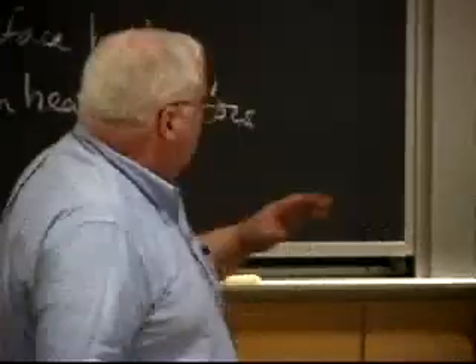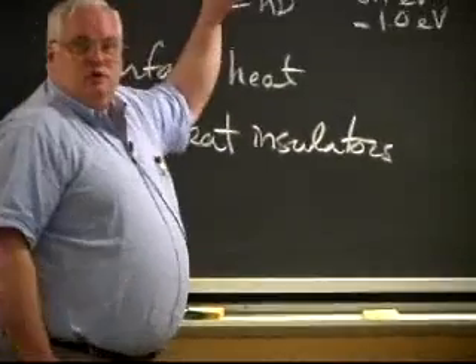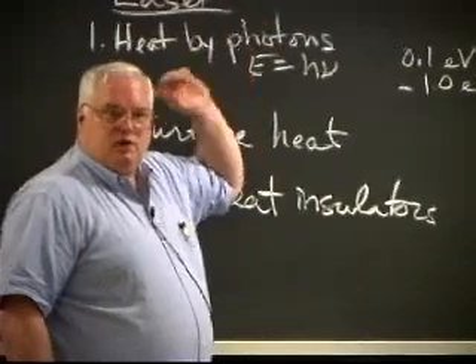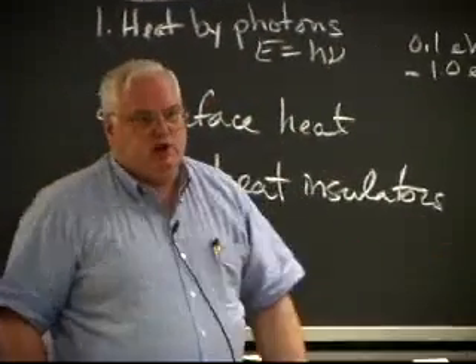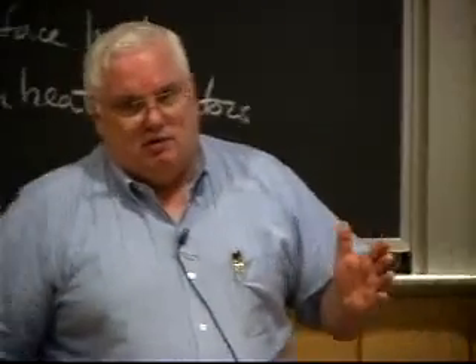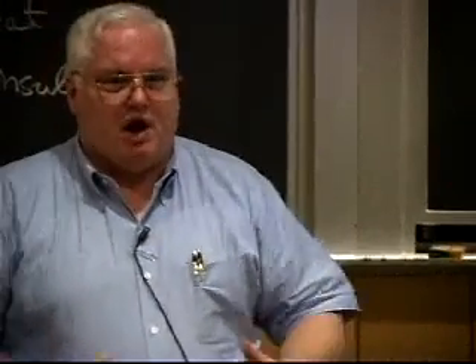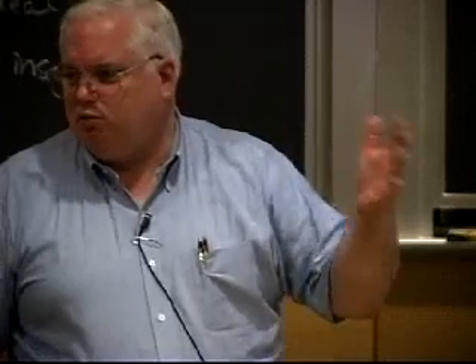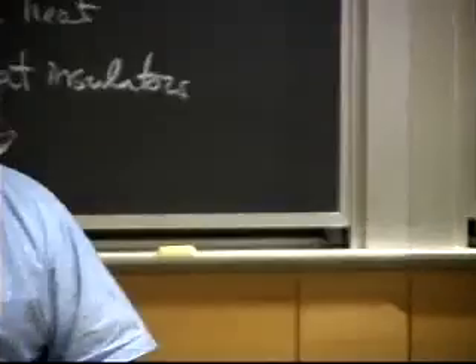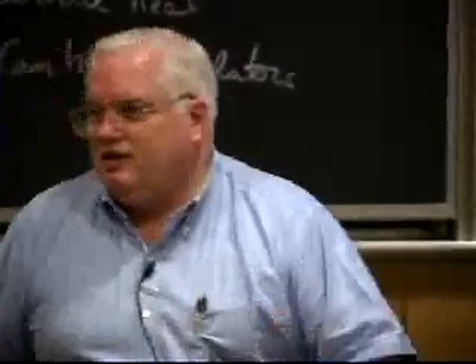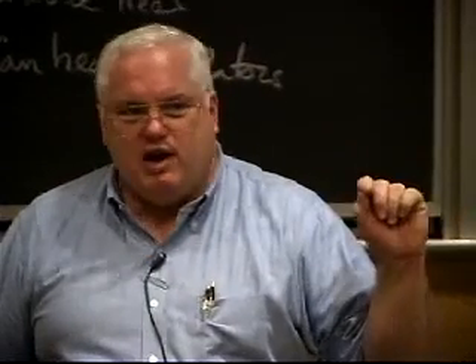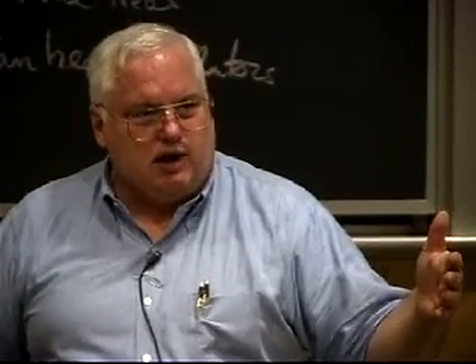And that's another reason why lasers on metals don't give you the same depth of weld pool as you'll get with electron beams. You're going to lose 70% of your heat just by reflection, which can be a problem. Which is why if you go into a laser shop, they'll have simple plexiglass, sometimes smoked plexiglass, because people think the smoke keeps the light down. It doesn't matter whether it's smoked or not. When you're talking infrared radiation, the plexiglass stops it. Smoked plexiglass, so people think they're looking through sunglasses, is really just cosmetic. Infrared radiation will not go through simple plexiglass; it'll just vaporize it.